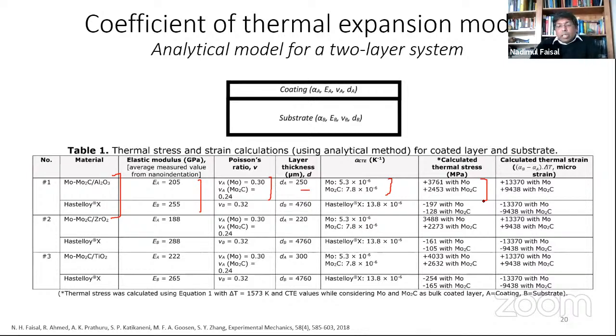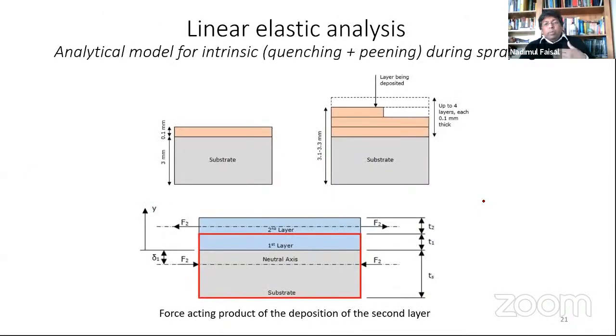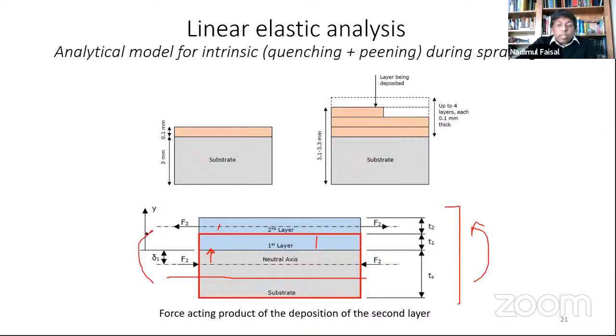So in my opinion, doing analytical calculation is good to understand, but it is not a very real value. It may be useful for some other technique, but for thermal spray, I don't think it is so helpful. Because if you do layer by layer, the dynamics, the strain which builds up in the substrate, will change because the neutral axis with the thickness will be shifted. For a single layer, the neutral axis will be somewhere here, but if you build up another layer, the neutral axis will shift. And then that can lead to a bending of the sample. It depends on tensile or compressive residual stress.